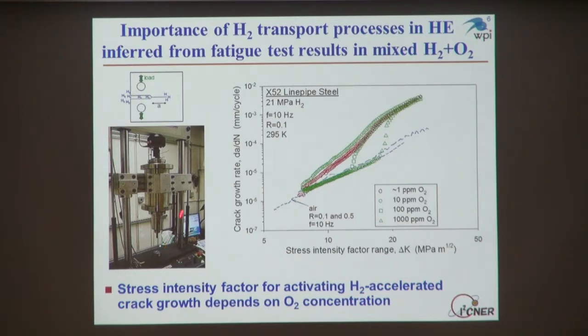And we do this testing in devices that look like this. This is a pressure vessel that's in the load train of a mechanical test frame. So we have to put these specimens inside these pressure vessels, fill the vessels with the hydrogen gas environment, and then we can apply the cyclic loading in concert with exposure to the hydrogen gas environment. We have one of these capabilities at Sandia. There are numerous of these capabilities here at Kyushu University, which really does make this one of the premier institutions for studying these types of effects.